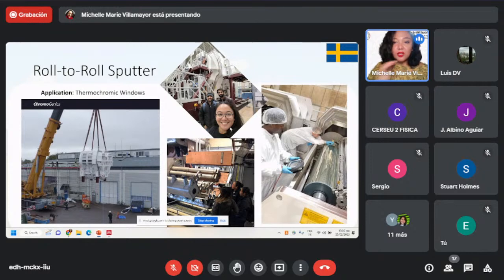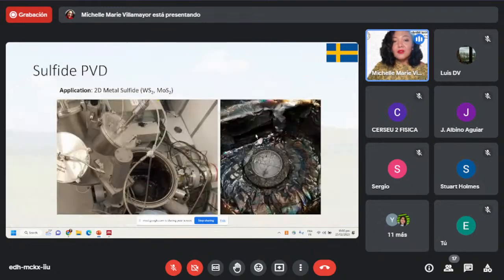However, there are some chambers which don't need to be clean. One example of that is if you are going to deposit 2D metal sulfides, for example, tungsten disulfide or molybdenum disulfide. The reason for this is these items here actually become a sponge of sulfur. And if we are going to do a deposition, the sulfur gets released from the sponge and helps in the deposition of the 2D layered material. And using sputtering, we were able to deposit these 2D metal sulfides onto a 4-inch wafer.